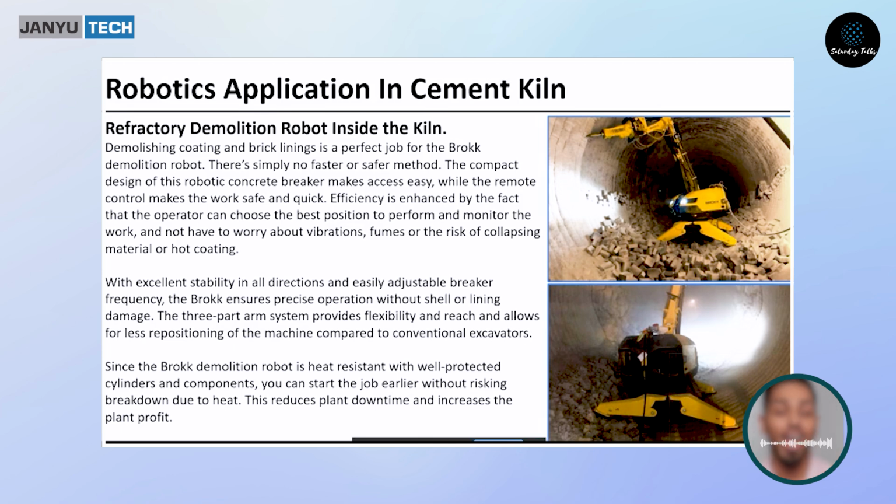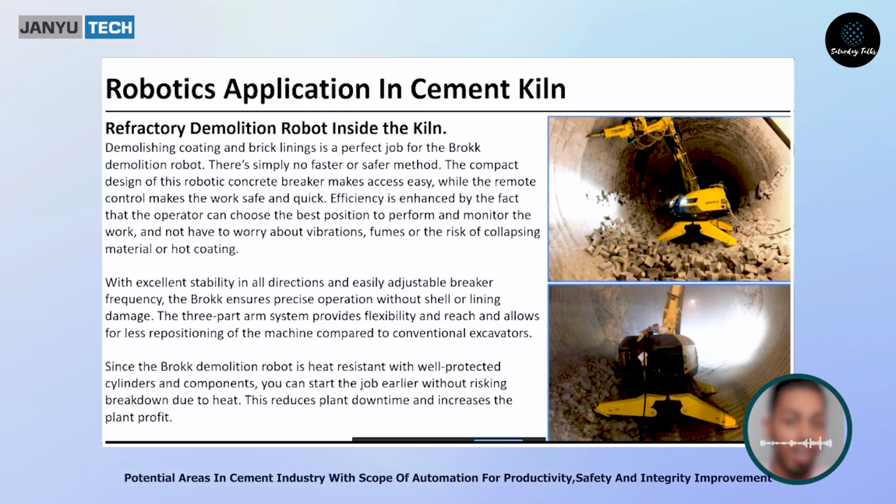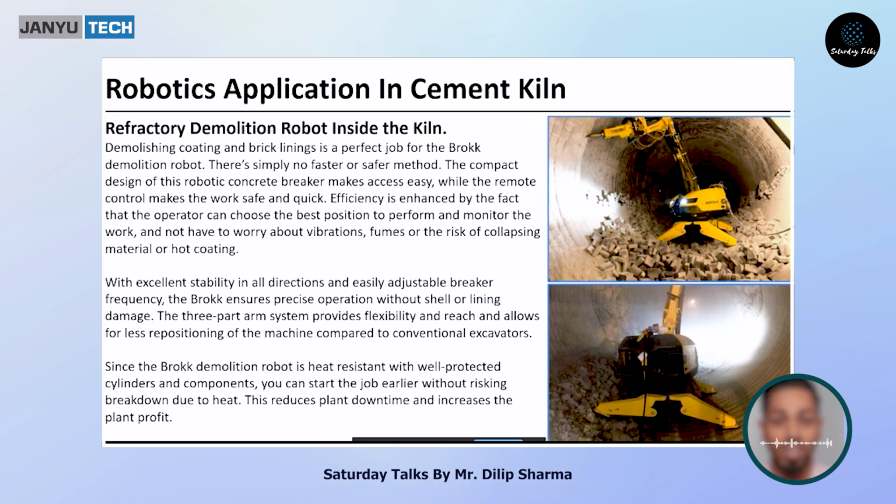We give 36 hours for cooling the kiln. After that, this machine is inserted immediately and debricking is done for almost 80-85 meters.